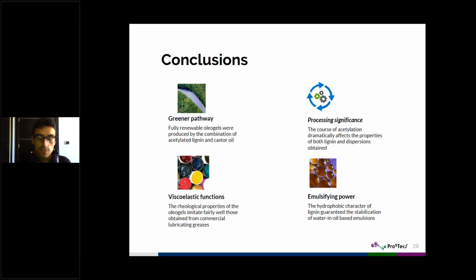Well, finally, I wish just to read some of the conclusions that we have obtained. First of all, we have obtained a greener pathway to obtain fully renewable oleogels just by the combination of acetylated lignin and castor oil. So we did remove those cross-linkers that were harmful beforehand.